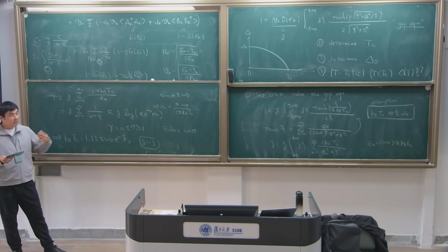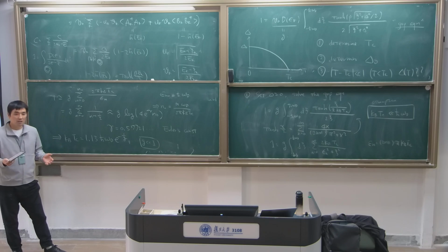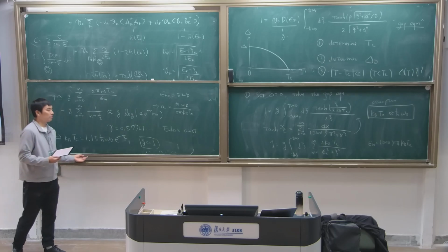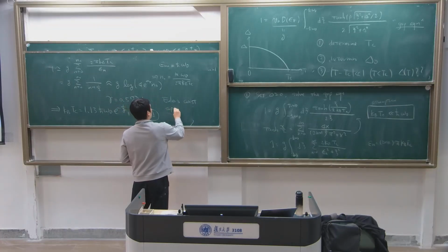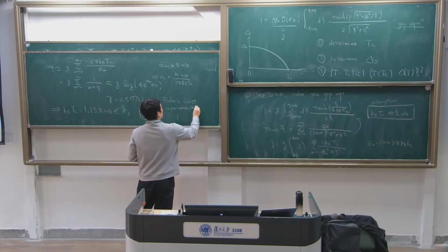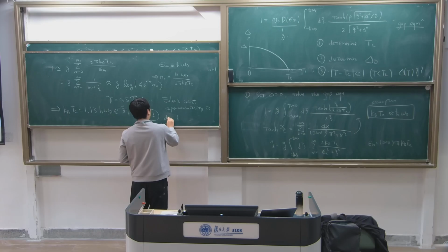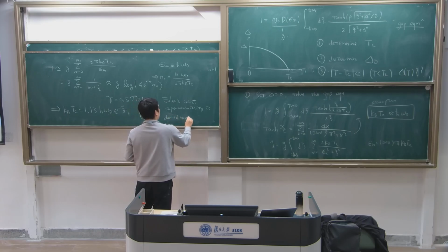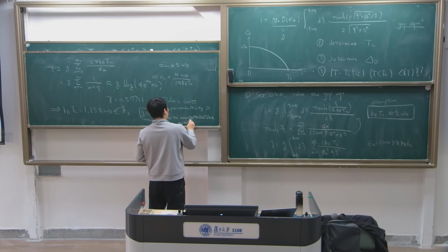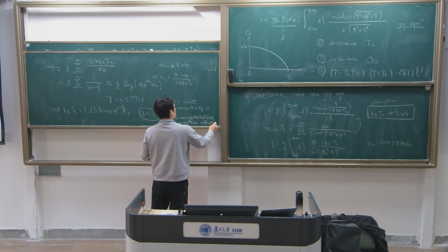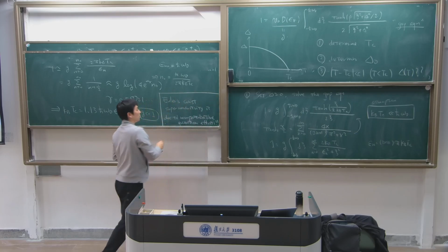In any case, this is very typical in superconductivity. You cannot use perturbation theory to derive superconductivity. So there's a really quantum effect, a non-perturbative quantum effect. This means that superconductivity is due to non-perturbative quantum effects. That's the main message this calculation tells.